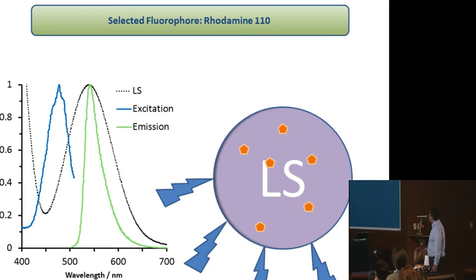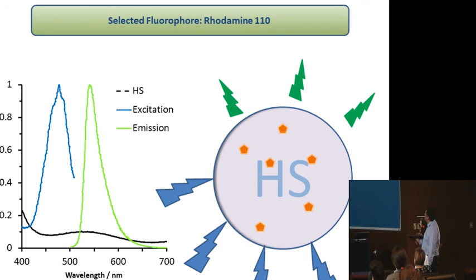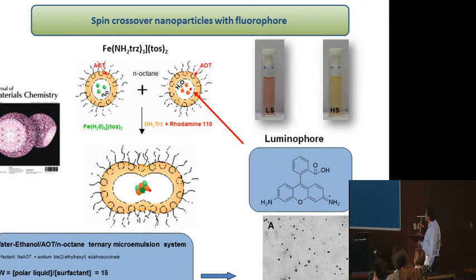I think you understood. So here we repeated the reverse micelle synthesis, adding the luminophore in the reaction, and modifying the experimental conditions a little bit. By increasing the temperature, it was possible to obtain 10 nanometer nanoparticles. Before, you obtained 4 nanometer nanoparticles with exactly the same conditions, but at room temperature. So by modifying the temperature, you increase the size of the particles.